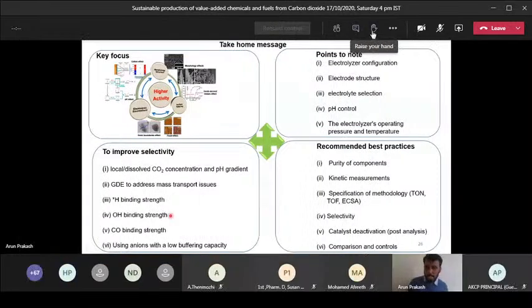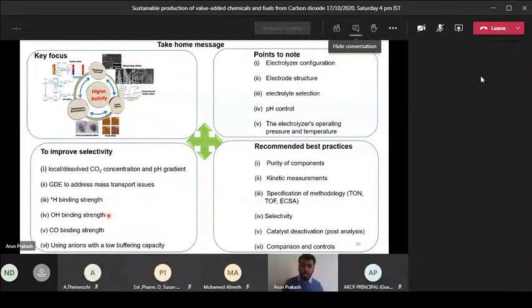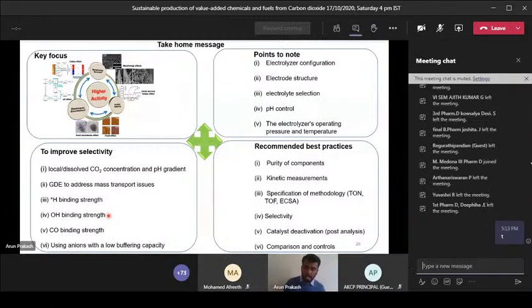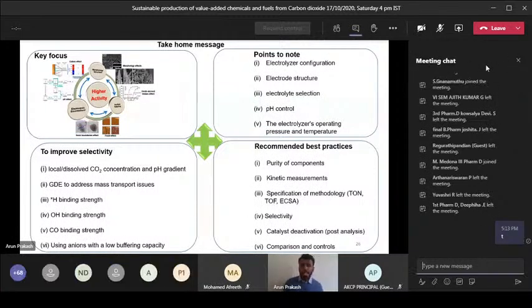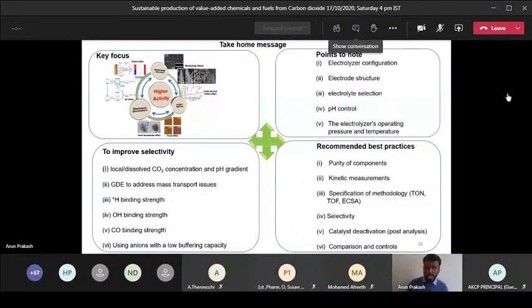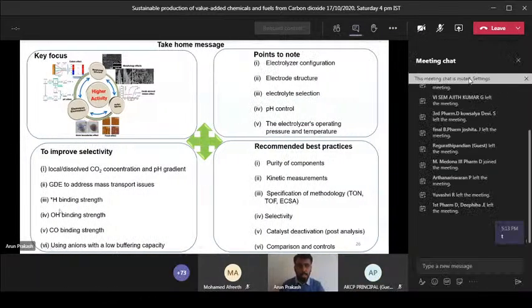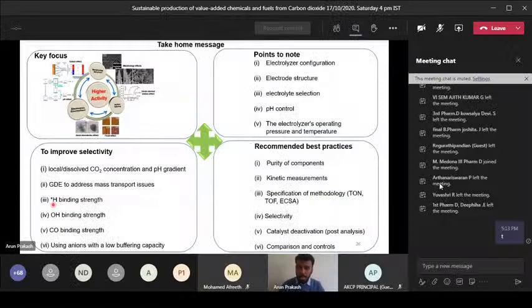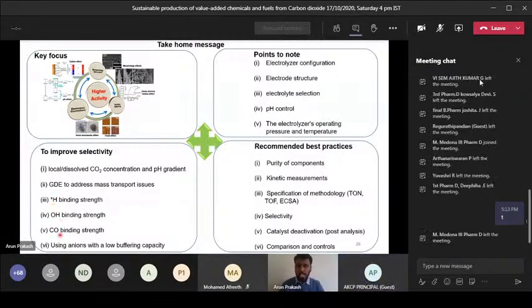When you want to understand your mechanism, you have to do some theoretical calculation like DFT and try to grab the adsorption energy information for your catalyst before doing the experiment. That will be very helpful. So you have to grab the information for the hydrogen adsorption energy, and the hydroxyl and carbon monoxide binding energy strengths. And using anions with a lower buffering capacity is preferred for improving the selectivity.